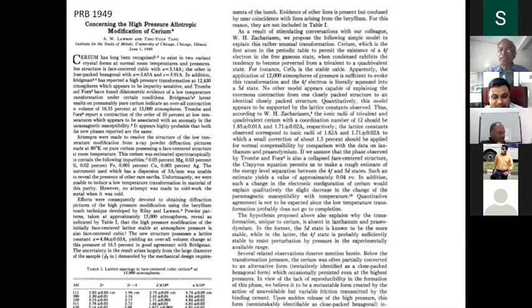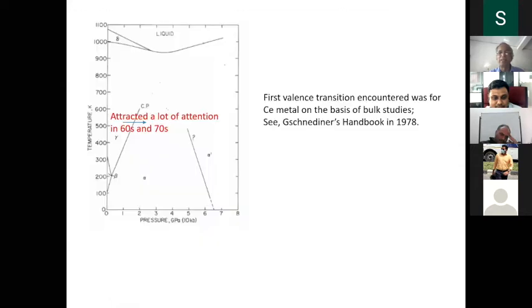Okay, and then these authors discussed with Pauling and Zachariasen. And again, I'm trying to tell you, they didn't take any credit for it. In the middle of the paper, they say, we discussed with Pauling and Zachariasen. And they proposed the idea that since the structure is not changing, there's a possibility the electron from the cerium 4f shell is going out and participating in the bonding. The reason why they proposed it is cerium dioxide. The example is here. Look, in cerium dioxide there is no 4f electron in the 4f shell. Okay, fine, it is possible. Therefore, the electron has completely gone out of 4f. So for the first time the concept was proposed: an electron can go out of the 4f shell, get knocked off, and occupy the conduction band. So the idea of valence transition was proposed by Pauling and Zachariasen in this 1949 paper.